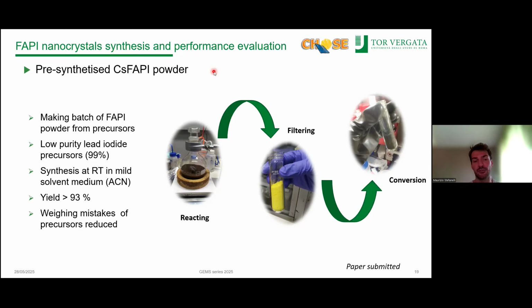And this is also a way to avoid weighing mistakes, because when we weigh all the powders from high purity precursors, for example, we can always have a human error, or an instrumental error, that can give us an excess of lead, or an excess of cations, that could be detrimental for the perovskite layer stability and also crystallization.